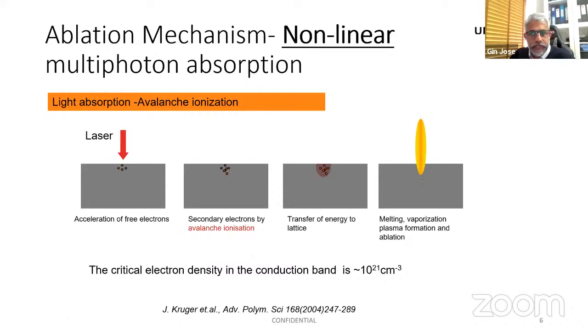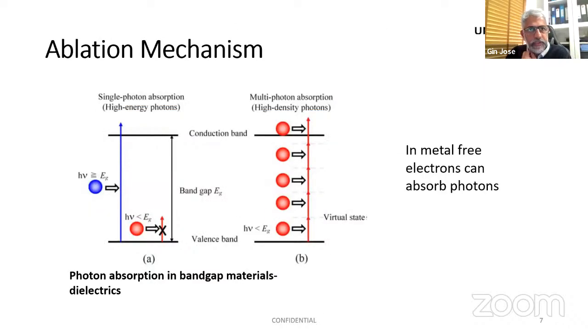It cannot stay anymore. It expands, and what you call ablation happens, and the material is basically breaking down. It's a very short process because the pulse is of very short duration. So there is not enough time for the heat produced at the focal spot to dissipate into the material. Before that heat dissipation happens, it evaporates or ablates the material from the surface. That's why it is also called the cold process, the ablation process using a femtosecond laser. So this is a simple description.